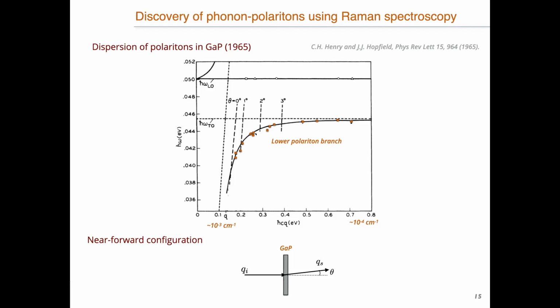Okay, so here we have the frequency, the propagation wave vector, the light line, and the TO polar phonon inside the material. Now let's look at the wave number that corresponds to the crossing of the light line with the phonon. We find that it's very small, 10 to the minus 3 inverse centimeter. In order to access this region, we need to launch polaritons that have very small wave vectors. The way to achieve this, I'll go into a bit more detail in the next slide, is by sending the laser light of the Raman system from this side of the sample.